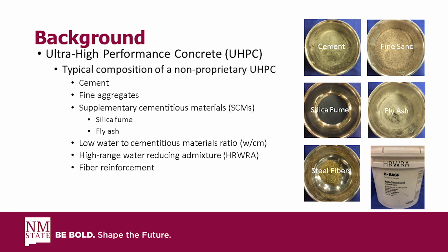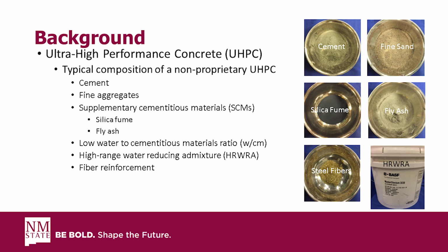And of course, we use supplementary cementitious materials, starting out with the silica fume, which is the main ingredient for this mix. It's the main contributor to our early strength gain and to our bond development, because it's a nanoparticle that has the ability to infiltrate void spaces. Whatever void spaces are available in that substrate, it'll develop the bond there. And our other material is a fly ash, which is a class F fly ash, and those two SCMs are in the two middle photographs there, with the silica fume being the darker material and the fly ash the lighter material.